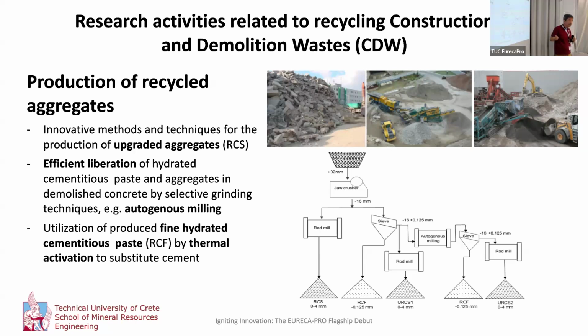The percentage of these recycled aggregates which can be added to natural aggregates at the moment is limited, depending, of course, on the quality of the recycled aggregates, to 20%. But even with this quite low percentage, the volume of recycled aggregates which can be used is very high, because the demand for aggregates and concrete is very high.